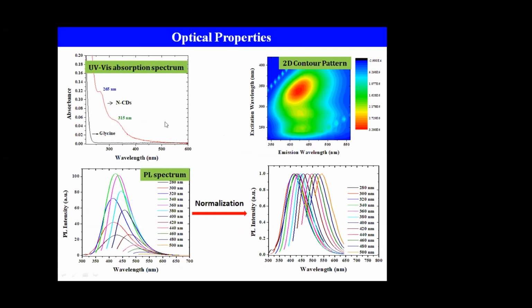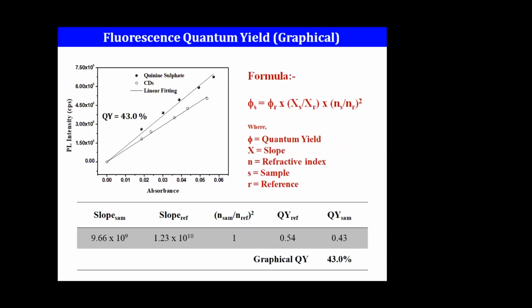And photophysical behavior, when you go for the fluorescence or luminescence. So you have the excitation wavelength dependency, and different types of absorption features. One can see it when you compare it to glycine, how exactly when you convert it into CD, absorption behavior changes. This is how one can see the synthesis of CD from glycine, and the quantum efficiency is the highest. One can see the 43% quantum efficiency of the carbon dot that we got from this material.